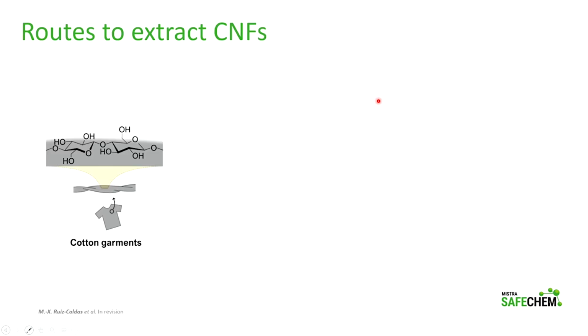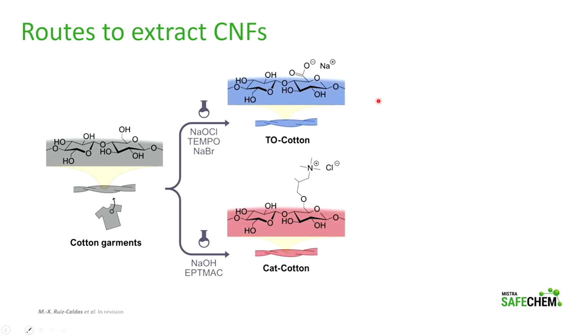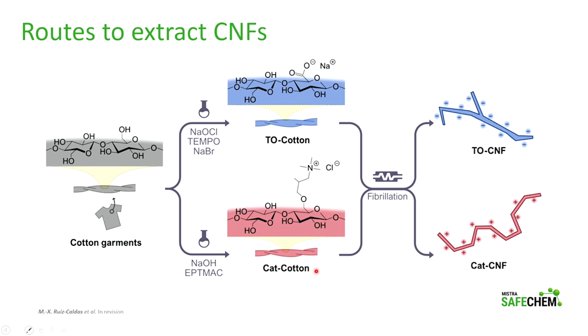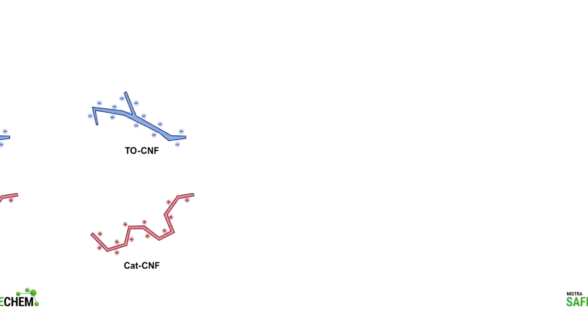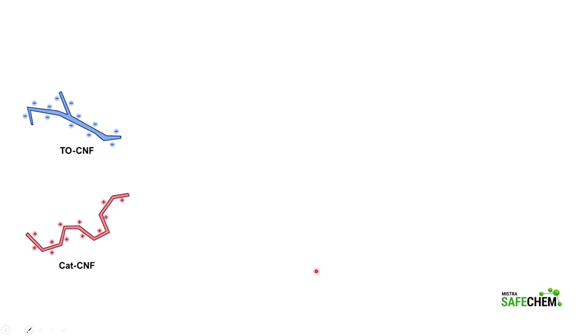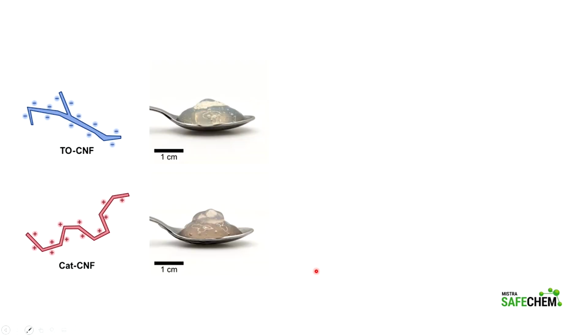The second type of material that I explained before was CNFs. So we also take these cotton garments. And then the first thing that we do is to give a surface charge. Here we aim for 2 different types of charge. So in the upper part, we have a negatively charged compound, and in the lower part, we have a positive one. And then through a mechanical fibrillation, we manage to isolate these long aspect ratio particles that I mentioned before.